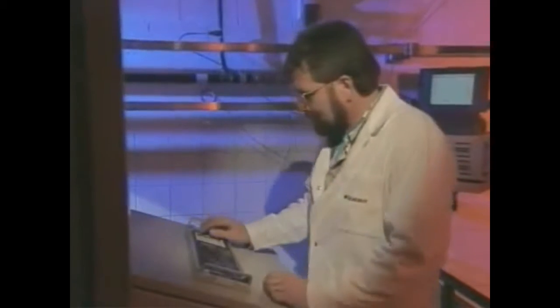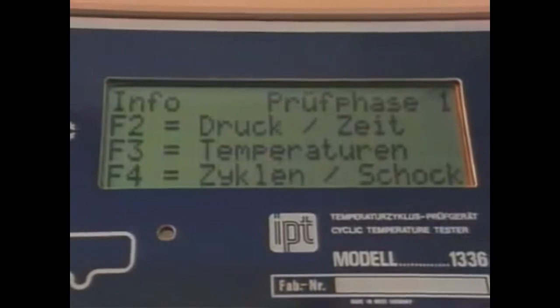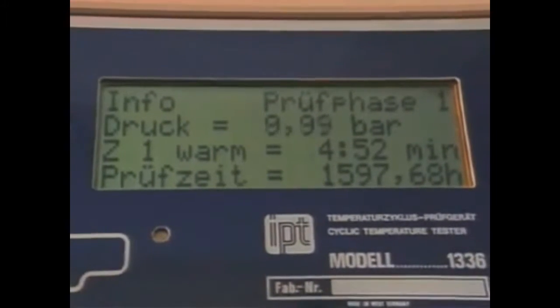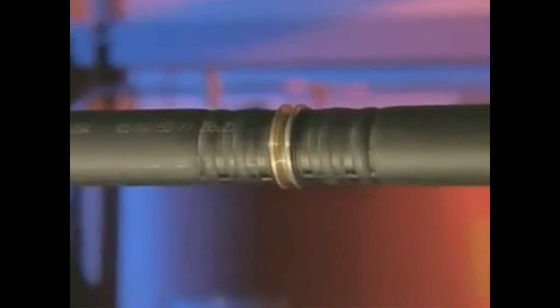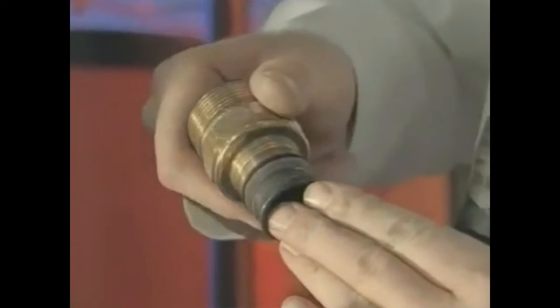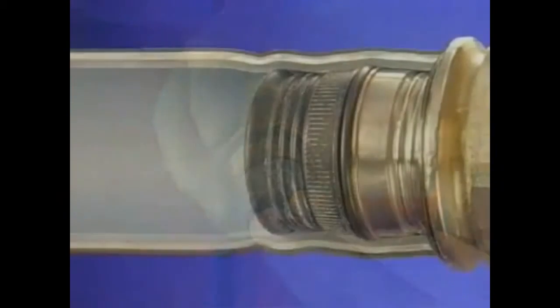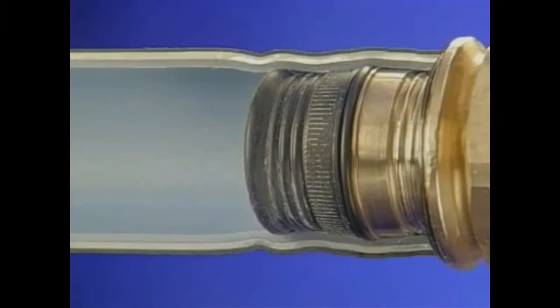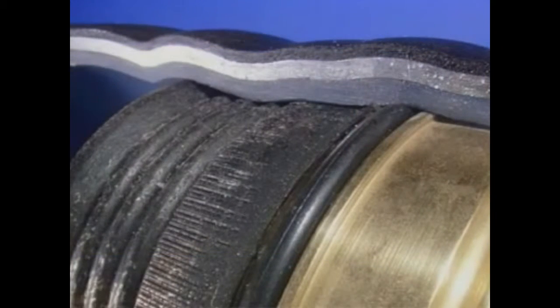Pipe connections must also withstand rapid temperature changes. In the test, the water temperature changes abruptly between 93 degrees and 20 degrees centigrade every 15 minutes. The test lasts for 3 months or more than 5,000 cycles. The fitting is then removed and checked. While the wet fitting end becomes discolored, the part behind the O-ring remains dry and bright. The test confirms that a perfect seal has been achieved.